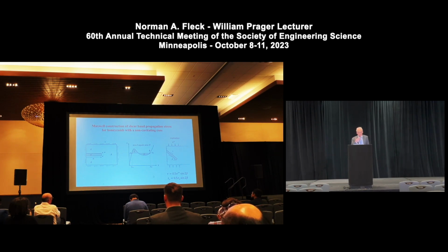So one can think of reducing this problem of a shear band propagating by just thinking of it as a problem in shear, as shown, and then by using essentially Mohr's circle, go back from the shear stress that's on the band to the uniaxial stress just simply by stress resolution. And that gives us the axial response, the axial stress, and equivalently the von Mises stress, the axial stress, in order for such a shear band to propagate.